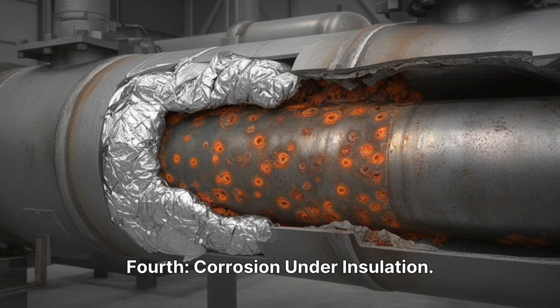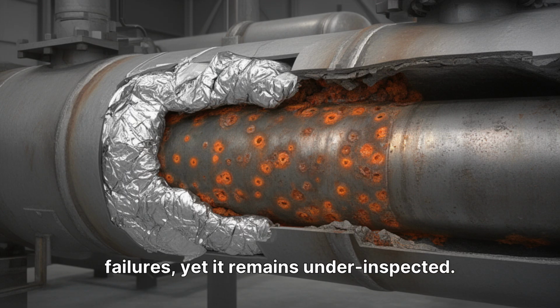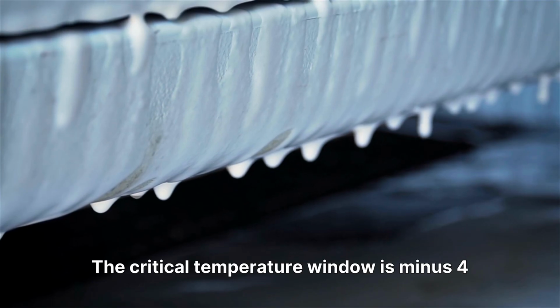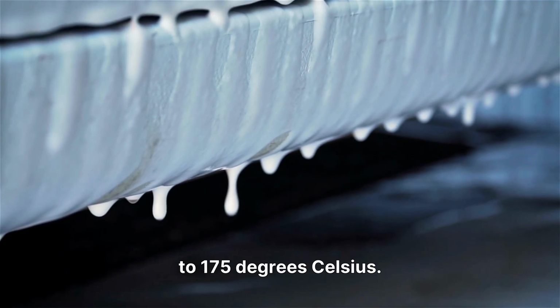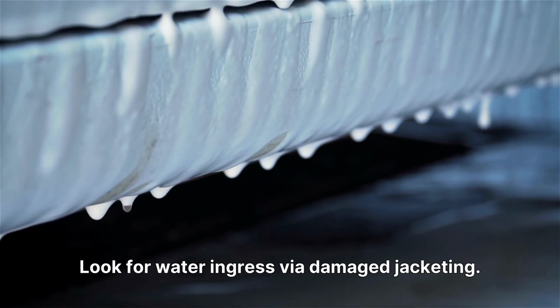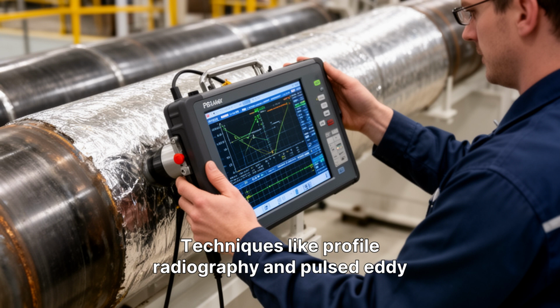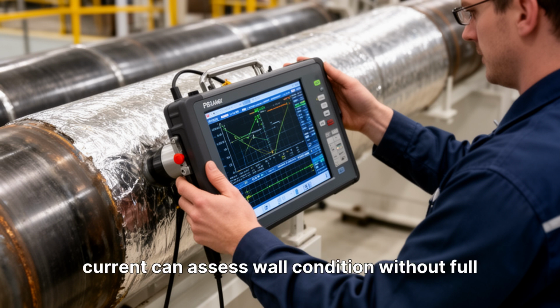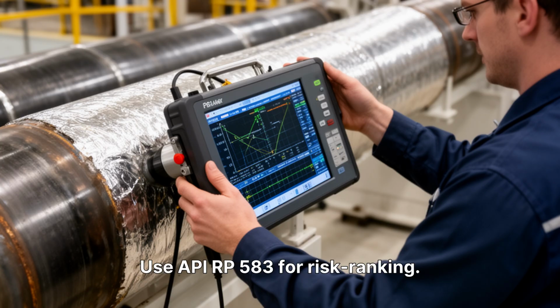Fourth, corrosion under insulation. CUI accounts for a massive share of failures, yet it remains under-inspected. The critical temperature window is -4 to 175 degrees Celsius. Look for water ingress via damaged jacketing. Techniques like profile radiography and pulsed eddy current can assess wall condition without full insulation removal. Use API RP 583 for risk ranking.